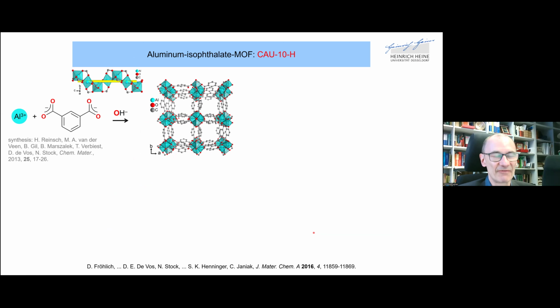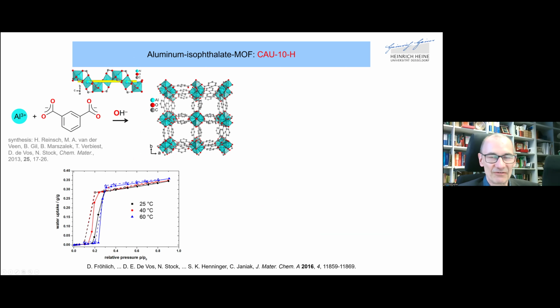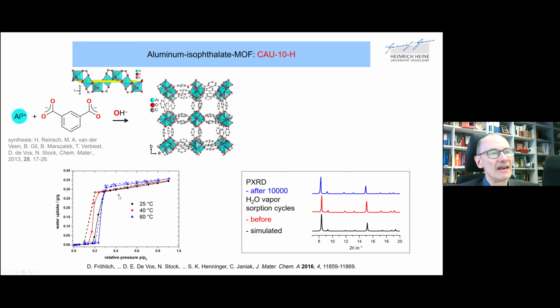And after we had discovered, together with other groups, that aluminum MOFs would be great MOFs for this type of application, there are other MOFs you could look at here, such as isophthalate, giving you the same or a very similar structure, and the uptake is also a little bit above 0.3 gram per gram. It changes a little bit with temperature, but otherwise has a nice S-shaped curve. And here the MOF could even be shown to be stable over 10,000 cycles, again judged by the powder X-ray diffractogram and also by the water uptake capacity. So there's no loss of water uptake over 10,000 cycles.